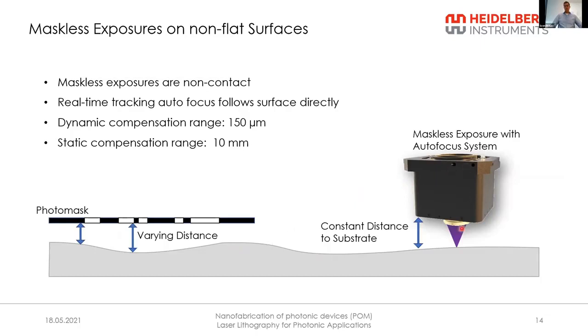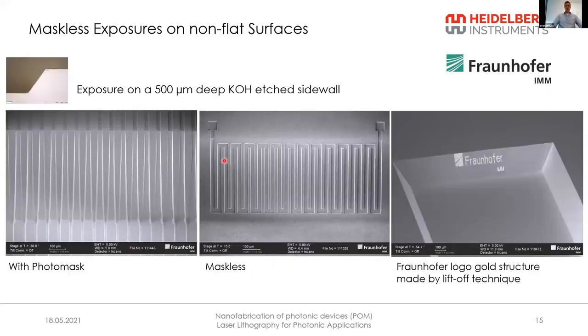The advantage of the maskless exposure is that it's a non-contact, and we constantly track the distance to the substrate. And during an exposure, we have a dynamic range of 150 micron, in which we can follow the surface, and the system has a static range of even up to 10 millimeters to do the exposures. And with this, you can expose on substrates that even have different levels, which is nicely illustrated in this example from the Fraunhofer. They had a wafer with etched trenches that were 500 micron deep, and they wanted to expose on the slopes of these 500 micron deep trenches.